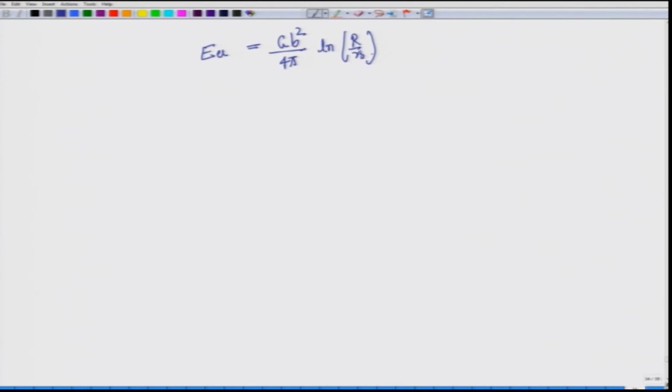When we integrated it, we simply put in r naught and r. r naught is very easy to realize, it is equal to the core radius, and core radius, as we said, you can take b to 4 b, or if you are talking about value you can take it equal to 1 nanometer. So, that part is solved, but what about r? What should we take the value of the uppercase R, which is the outer limit up to which we should calculate the elastic strain energy?